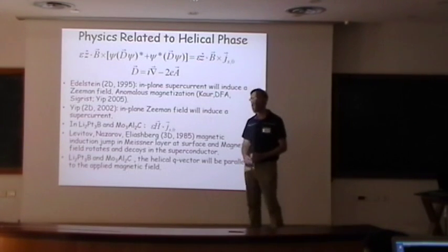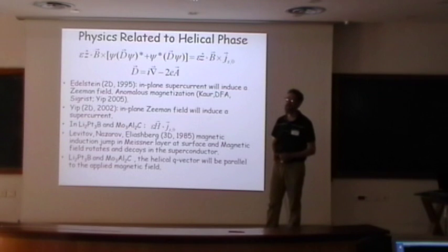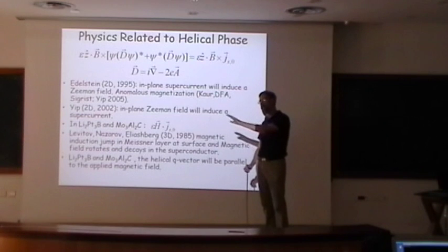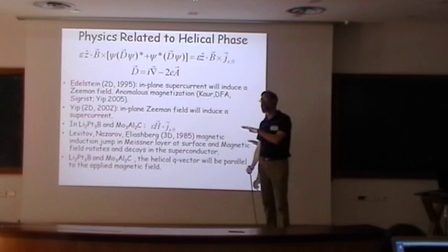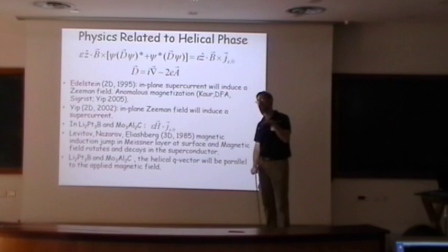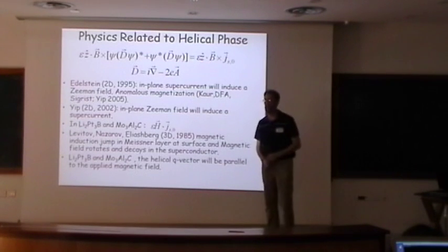Maybe a naive question, but these Ginzburg-Landau free energies and these extra terms, these Lifshitz invariants, you just write them down because they allow the symmetry, or you derive them from microscopic theory? You can also derive them from microscopic theory, and this is actually what Ilya asked about. It turns out this Lifshitz invariant is proportional to this delta n factor. So that's relevant. And I didn't mention this before, but it is possible to have delta n equal to 1, and that's exactly the case of the surface of a topological insulator with superconductivity. In that case, delta n is actually 1, and so then you always get this helical phase showing up.